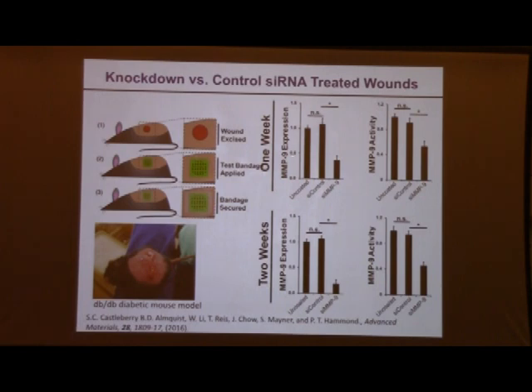What you can see on the right is the amount of gene expression of MMP9, where we normalize against the uncoded control. We look at the control and see little to no difference, but with the MMP9 dressing, we see decreased MMP9 expression. If you actually measure the activity of the protein in the wound, here you can see MMP9 activity is also lower. This is after a 1-week period. After a 2-week period of the bandage on the wound, we see that we've lowered MMP9 expression by about 85%. So we have a very real delivery of siRNA within the wound that is sustained over time.